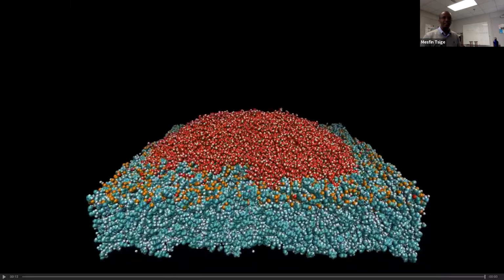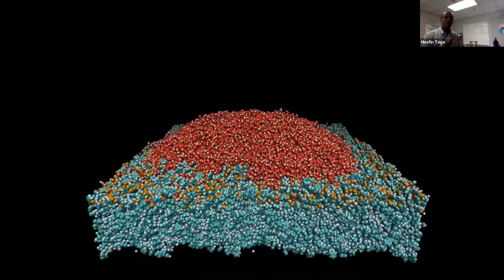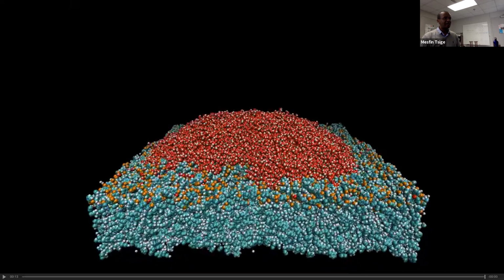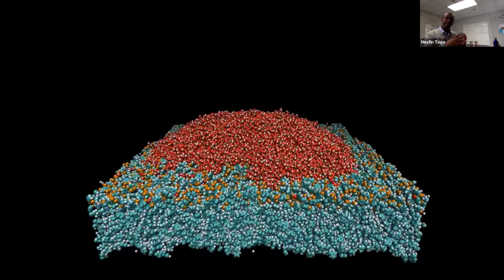What we have done is we oxidized the phenyl groups in the top 2 nanometers of the film. And this orange that you see are the oxygens that are attached to the phenyl rings, and the red are the oxygen of water molecules. So there is diffusion to the top couple of nanometers and at the same time wetting. So the process is slightly complicated. You have a combination of different processes that are taking place.